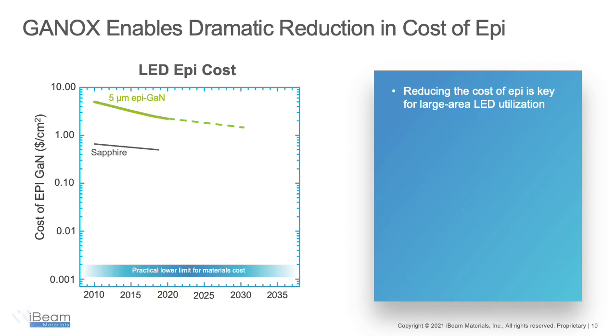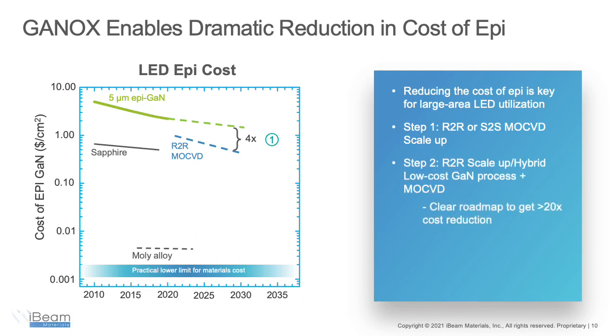Now, 20% of the current cost is just the sapphire substrate cost. If we go to roll-to-roll or sheet-to-sheet MOCVD scale-up, one can reduce the cost by, we believe, at most a factor of 4 in keeping MOCVD. However, by going to a hybrid process where one uses a lower cost deposition process for the gallium nitride buffer layer, one can reduce the cost, we believe, by another factor of 5, bringing us to cost competitiveness with OLED materials deposition cost. This means that mobile displays can now be made using this micro LED technology.